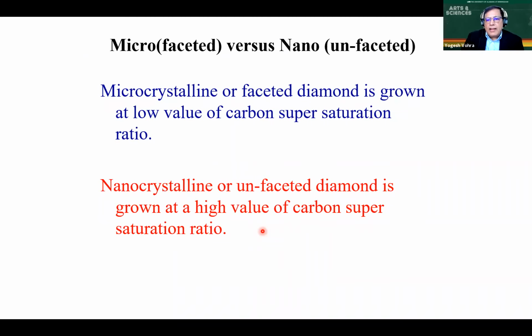What that is doing is the nitrogen molecule in the plasma is soaking up microwave energy, because the nitrogen-nitrogen bond is really very strong, and that leads to reduction of the energy available for producing atomic hydrogen. So the supersaturation ratio S increases when you add nitrogen, and that's why we get the nanocrystalline. So this is a kind of simple explanation for nitrogen-induced nanocrystallinity. There are other ways to produce nanocrystalline film by just upping the carbon concentration in the plasma, and that also gives a nanocrystalline diamond film deposition.